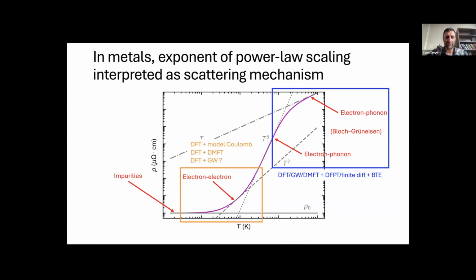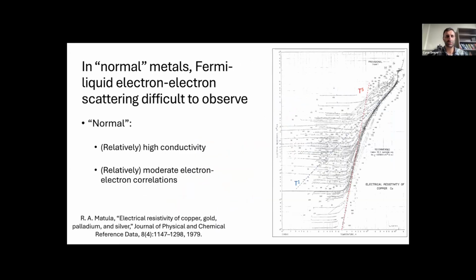There's been a lot of work in this community on this electron-electron part of the resistivity because, of course, in strongly correlated materials, this can dominate over the electron-phonon part. As Antoine said, I come from a more conventional electronic structure background, and there the electron-phonon part has been the dominant area of improvements in techniques and calculations of materials. The reason that has been the case is that this electron-electron regime in what I would call normal metals is actually very difficult to see experimentally.